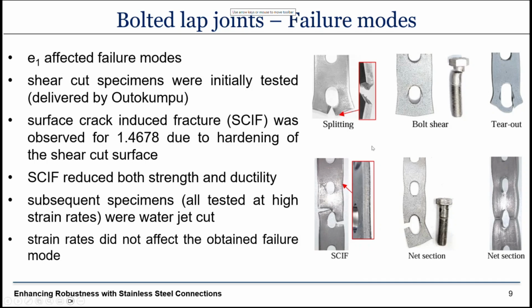Which brings me to the discussion on the failure modes. Here we can see typical failure modes on this slide. For specimens designed to fail by bearing, the distance of the center of the bolt hole from the edge, E1, was varied. And as we increased E1, the bearing resistance was increasing. At some point, we shifted the failure mode from tear out to either shearing of the bolt or net section fracture. So at some point, bearing resistance was more than the net section fracture or the shear resistance of the bolt.